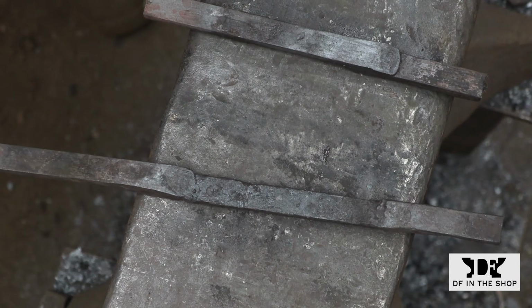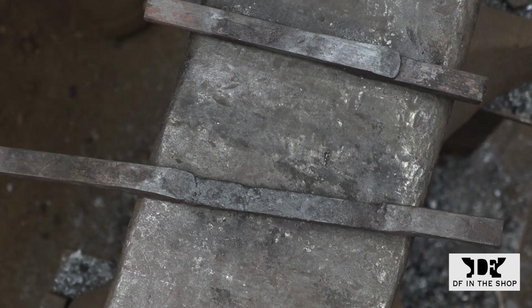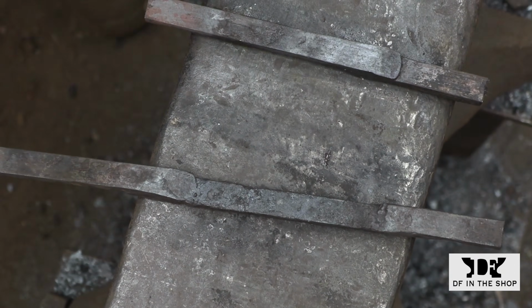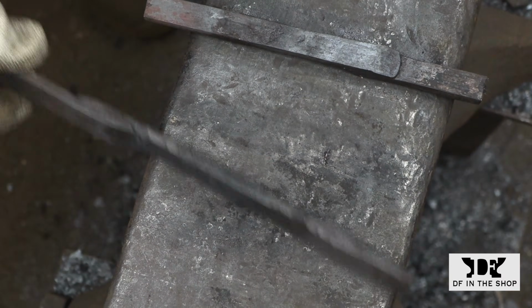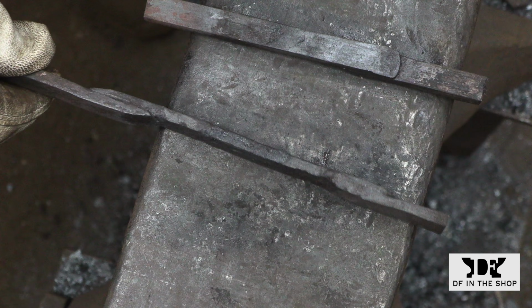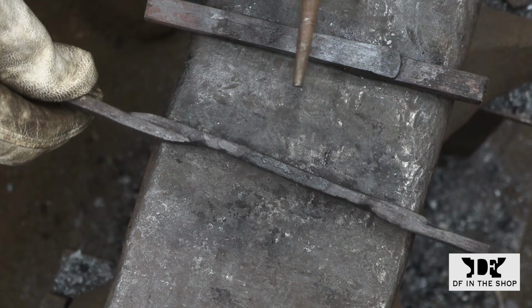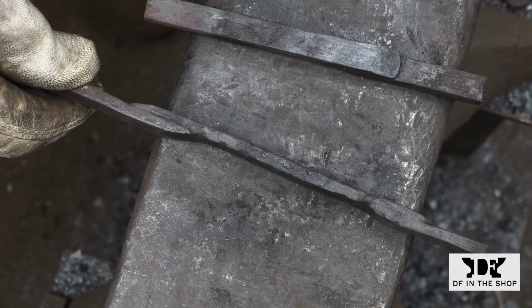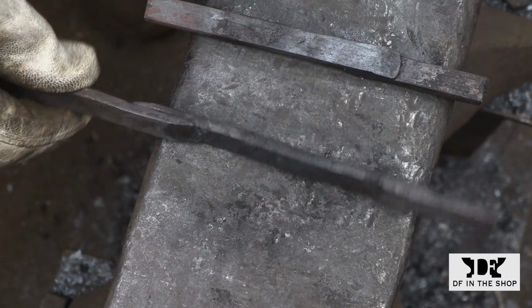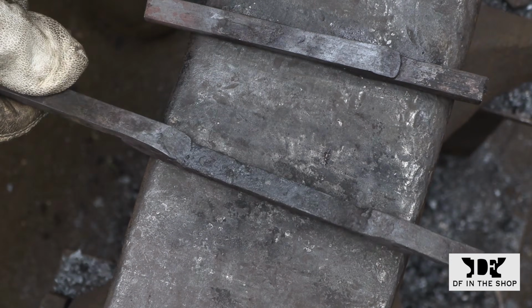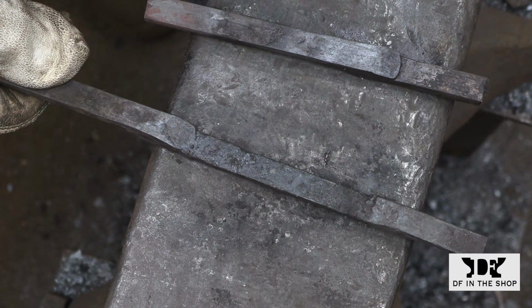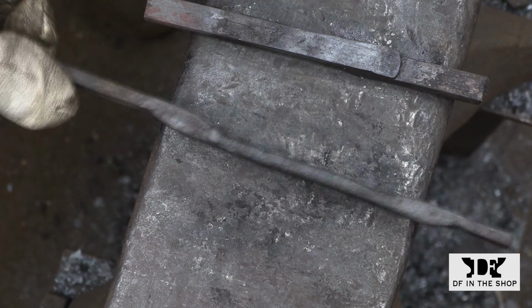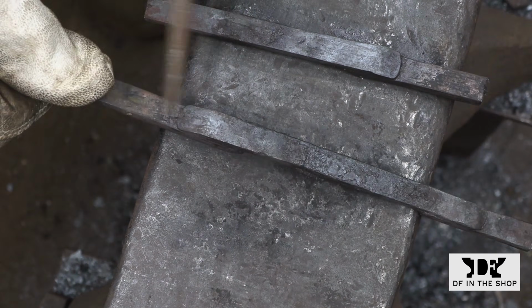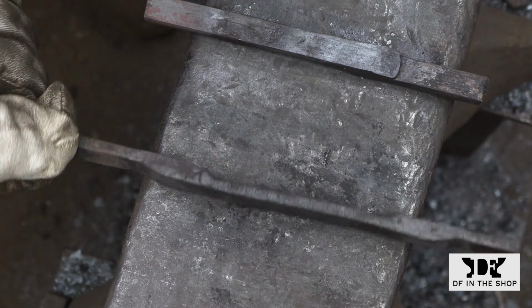This is the sample of the welds that I just completed. The one closest to my hand is the first weld that I did with the overlap that was much longer, and the one at the other end of the bar is the second one that I did with a much shorter overlap. You can see how the first weld that I did isn't quite as far along because I have to take two heats to cover the full length of that weld, whereas the second heat, my hammerhead covered the whole length of the weld, so I was able to get a lot more work done.